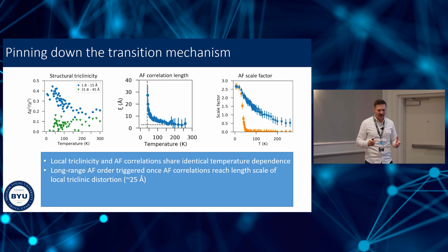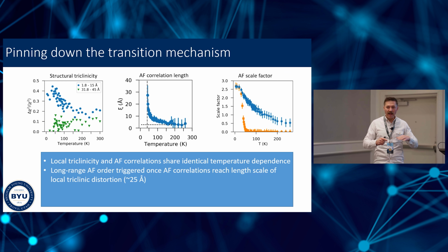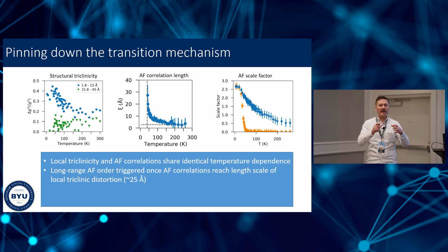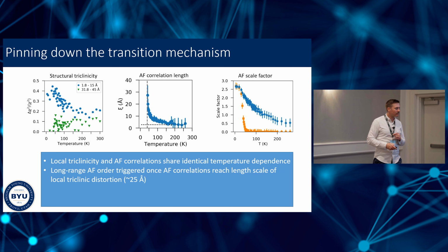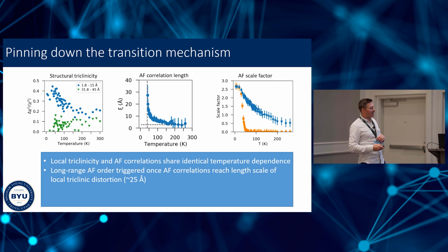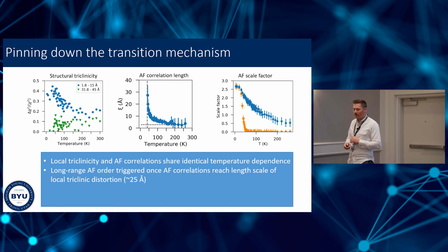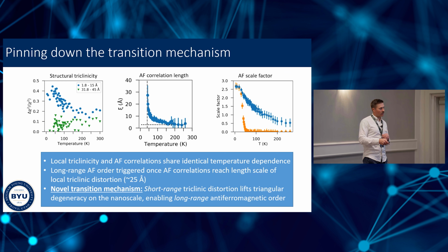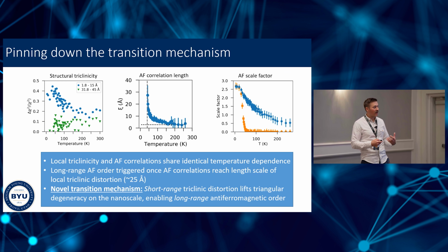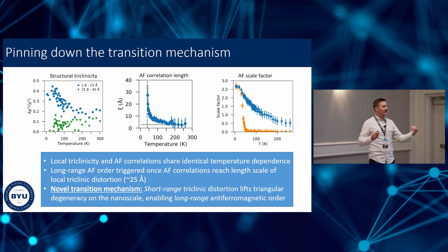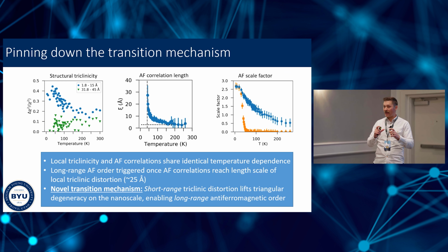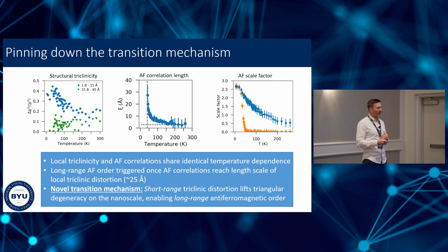So what does this mean? This means that the local triclinic distortion allows the growth of those antiferromagnetic correlations within that distorted triclinic region. And then as soon as those magnetic correlations have a long enough length scale to bridge these different locally distorted triclinic regions, that's when long-range magnetic order is triggered. So this is an interesting transition mechanism for a frustrated magnet. We have a short-range triclinic distortion lifting this triangular degeneracy on the nanoscale, enabling long-range antiferromagnetic order once the length scale of the magnetic correlations matches the length scale of that local triclinic distortion.